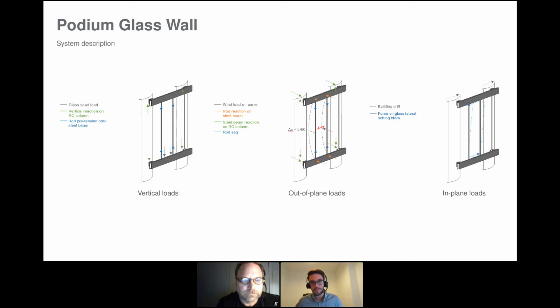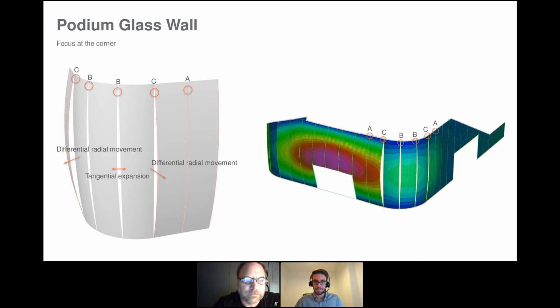As we were looking at the plan of the tower, we have these rounded corners that are probably the most interesting area of the full facade. That's because the different geometry between flat and curved panels has an intrinsic influence on the stiffness of the panels. Therefore, what we had to do was identify the main different interfaces: between flat and curved panels, flat and flat panels, and curved and curved panels. As you can see here on the screen, position A is the typical interface between flat panels, position B is the interface between two curved, and position C is the interface between flat and curved. Each of these interfaces can experience differential behavior in terms of movement.